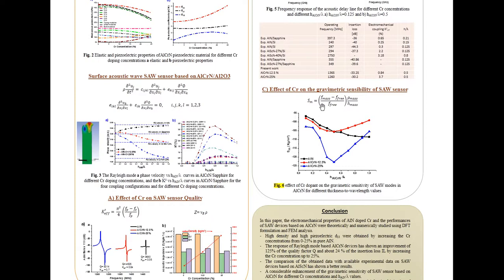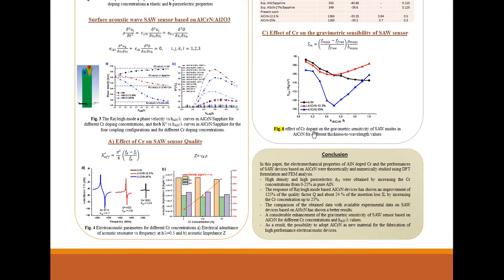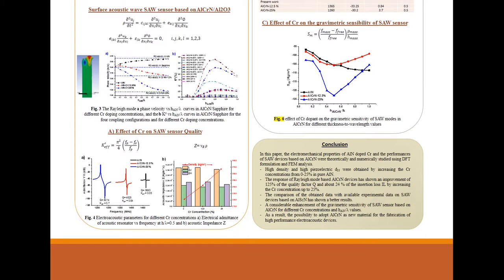and the study has also revealed a considerable enhancement in the gravimetric sensitivity of SAW sensors based on aluminum nitride doped with chromium. Finally, we conclude this presentation by the following remarks. High density and high piezoelectric D33 were obtained by increased chrome concentrations in pure aluminum nitride.